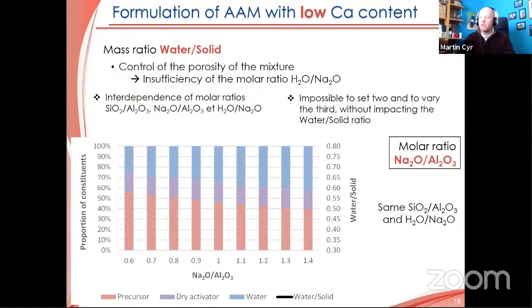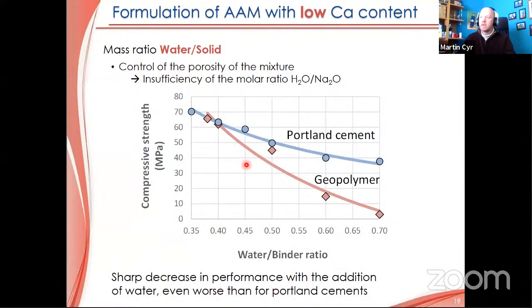And at the end, if we have a look at the water-solid ratio, it's the black curve here, we see that if I try to keep this value constant and change only this molar ratio, sodium over aluminium, it means that it will increase a lot the water-solid ratio. And since the water is not inside the structure, in polycondensation, as was said earlier, the water is mainly rejected, it means that it will leave a lot of porosity and it will have a strong influence on the mechanical properties. I'm showing you here the effect.